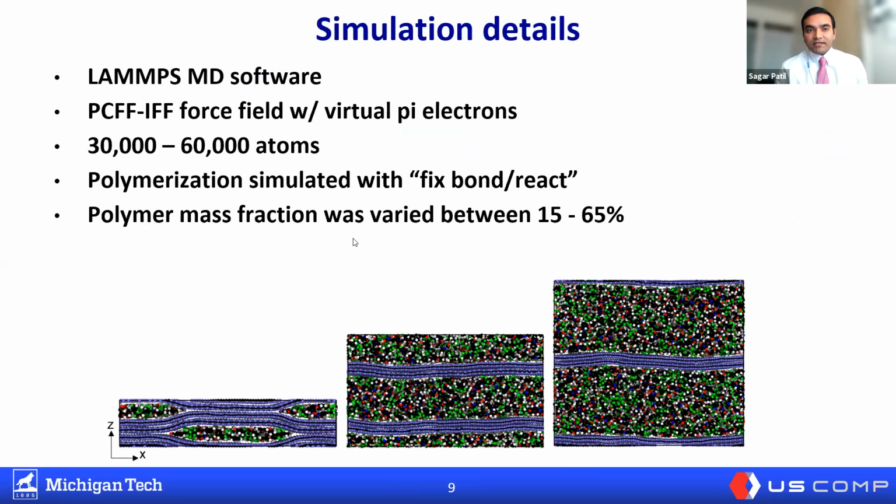So these are the simulation details. The molecular dynamics simulations are set up and run through LAMMPS software. One of the key features of any molecular dynamics simulation is the choice and implementation of the force field. A force field describes the interactions between atoms within the molecules itself. So it is very necessary, and it influences the results a lot. In this case, I'm using the polymer consistent force field, interface force field, which is proven to accurately describe these interactions.